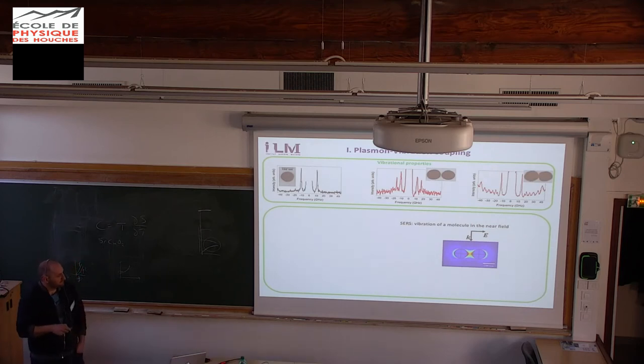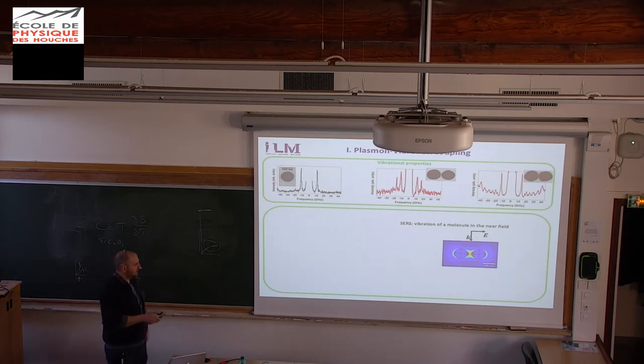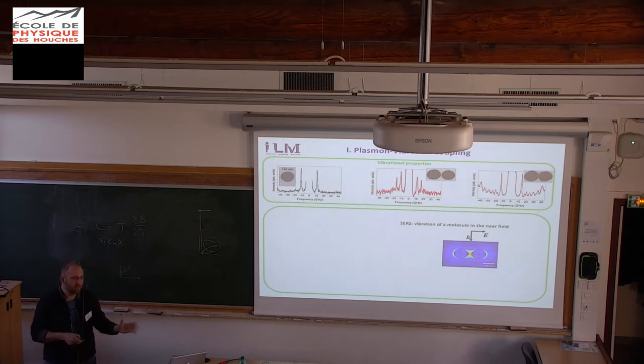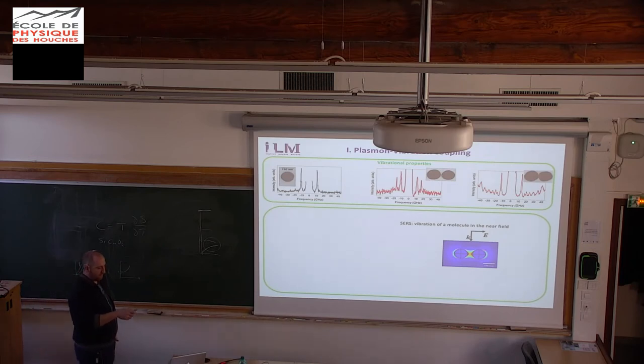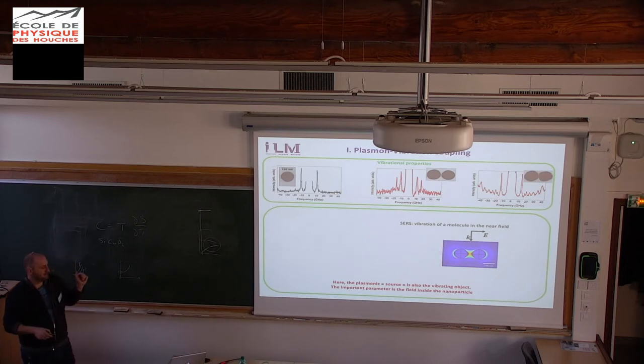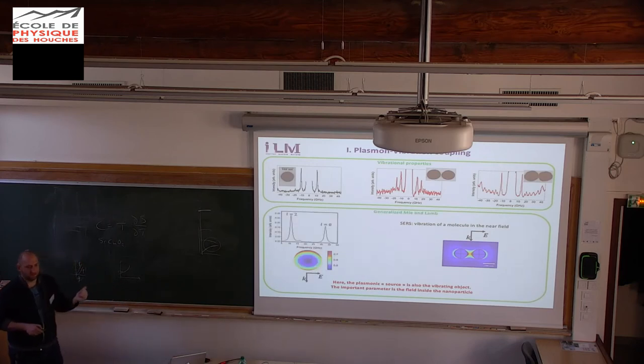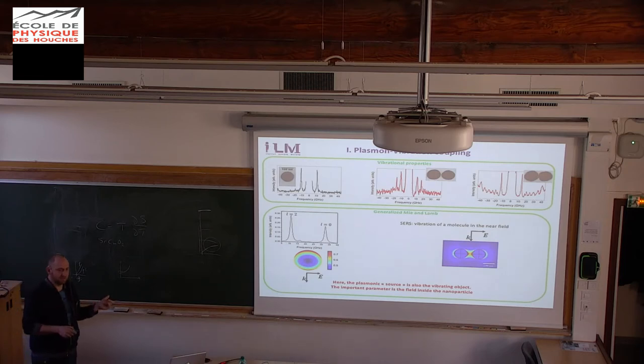So I will just discuss this. I do SERS, so this is clearly the SERS representation. What is important when you are doing SERS at high frequency is the field in between the nanoparticles, because you put your molecules inside this field. In our case, the source of the plasmonic enhancement and the vibrating object are the same. So what is important is the field inside the nanoparticles. We have to consider the field inside the nanoparticles.